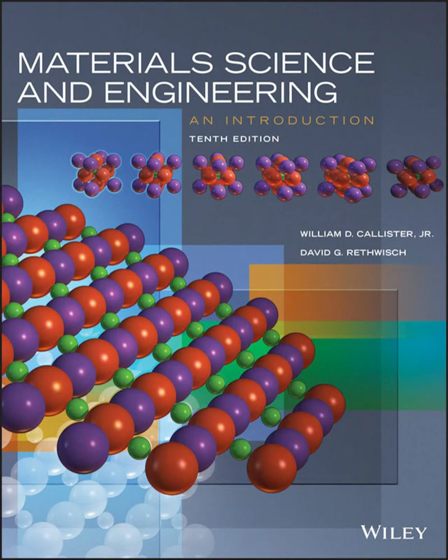That's right. And we generally explain this atomic motion in metals using two main mechanisms. The first one is vacancy diffusion. So picture that regular crystal lattice, that ordered arrangement of atoms. Now remember, there are always some missing atoms, empty lattice sites. We call these vacancies. In vacancy diffusion, an atom on a normal site essentially just swaps places with an adjacent vacancy. The atom moves one way, and the vacancy effectively moves the other way. So this mechanism absolutely depends on having those vacancies present, and their numbers increase a lot at higher temperatures. More vacancies mean more chances for atoms to jump.